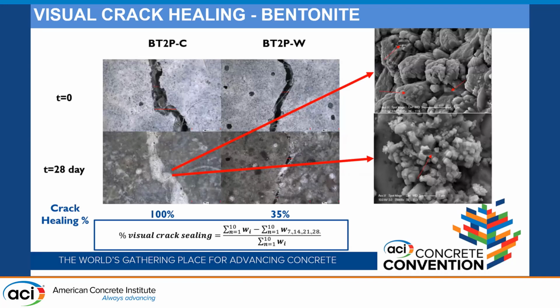Cracked beams are periodically observed under a stereo microscope. The percent of crack closure was determined by a Java-based image processing program called ImageJ. The crack width measurements were taken at 10 different points on each crack sample after 7, 14, 21, and 28 days of curing. The crack closure was calculated according to this formula.